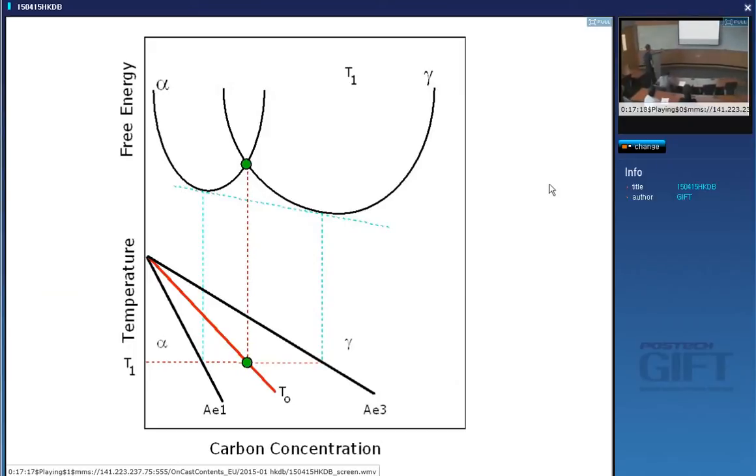So we've solved everything about the crystallography of martensite, but you are also interested in other aspects of martensite. For example, what temperature will it form at? The driving force for martensite, because there's no composition change, is very simple. If I have an alloy here and I form martensite, then this is the free energy change, right? There's no composition change. If I'm on this side and I transform to martensite, I get an increase in free energy. That's no good. That's not possible. So there is a point here to the right of which you cannot get diffusionless transformation.